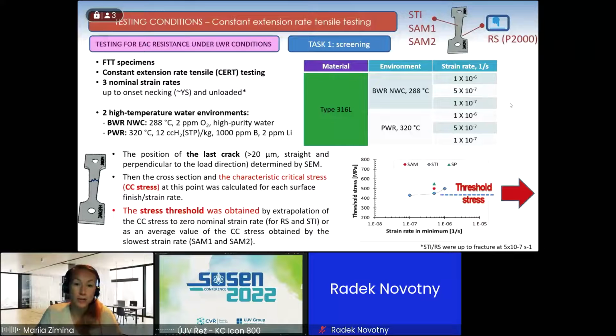So first task was accelerated testing for screening the conditions for the further stress corrosion initiation testing. So we used the FTT specimens with tapered specimens, and we performed accelerated constant extension rate tensile testing with different nominal strain rates, and in two different water environments, BWR and PWR. So after this test, we identified the position of the last crack, which has to be more than 20 microns in length and straight and perpendicular to the load direction. So it was determined by SEM analysis.